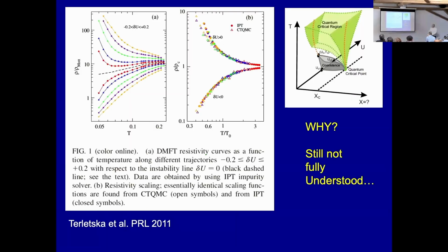And what they showed here, so these are calculations of the resistivity versus temperature in this higher temperature regime. You see that there is an insulating branch, there is a metallic branch. You've seen this in many, many systems that display a metal-insulator transition. And they were able to scale all this data. But now the scaling is completely different from the one I showed before. It's a scaling that involves T over some energy scale T naught and some dynamical critical exponent. So something that you would usually do if you are in the quantum critical regime near zero temperature quantum criticality.